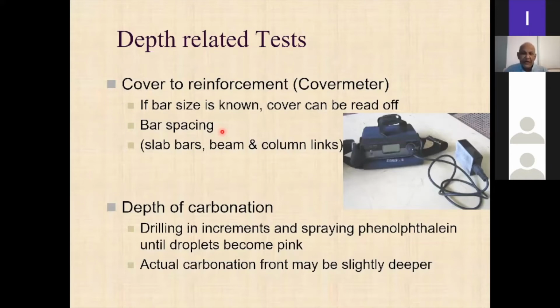So even if you use the correct yield strength, even if you use the correct bar diameter, instead of spacing at 150 millimeters, if you have spaced at 175 millimeters, then the moment of resistance will reduce. And using a cover meter, you can get the spacing of the reinforcement, right? Okay, so depth of carbonation, also you have to spray as soon as you take the core on a freshly cut surface, which is a core surface.